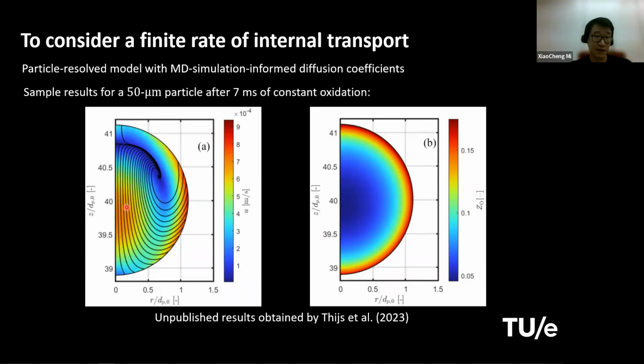You can see that inside the particle, you can even have some non-uniform distribution of a velocity, because the particle, for example, in this drop tube, there is a slip velocity between the particle and the gas. So the gas can give this momentum to the liquid inside the particle, and this liquid can swirl and create this non-uniform velocity field within the particle. And this is only with about 7 milliseconds after you supply oxygen to the particle, and you can see a clear gradient, spatial gradient inside the particle.